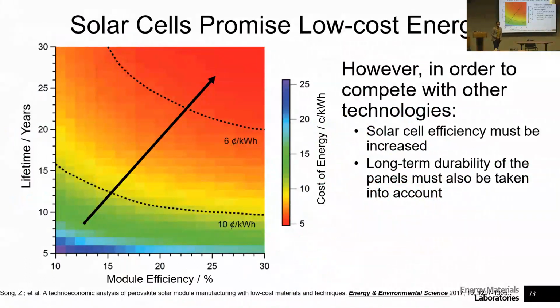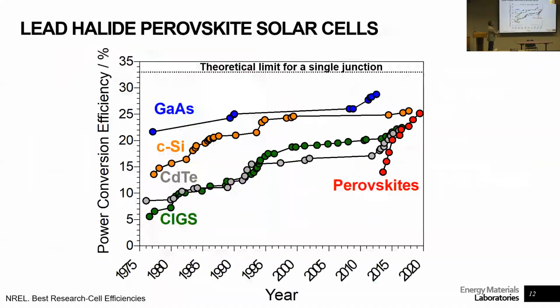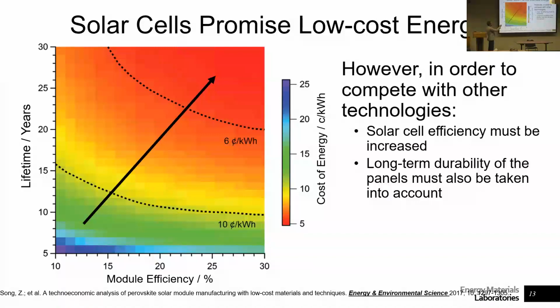And not only that, but also looking at the techno-economic analysis of some of these materials, we can see that we can have very, very low costs for that specific perovskite solar cell if we are able to get efficiencies in the 20 to 30% window, and lifetimes of 20 to 30 years, right? And actually this here is the biggest challenge. How can we make the solar cells last for 20 to 30 years like silicon? Because if we had that, I wouldn't be talking to you right now. I would have a startup and I would be making a lot of money. But really, if we're able to solve the lifetime problem, we would be able to make this technology basically replace any current state of the art.